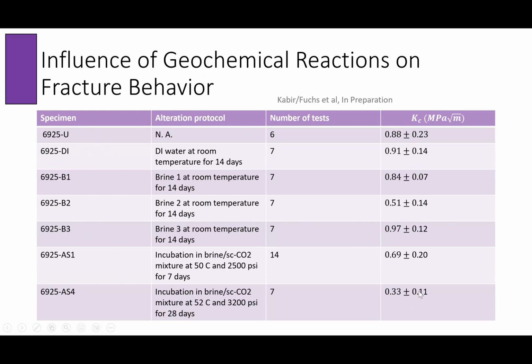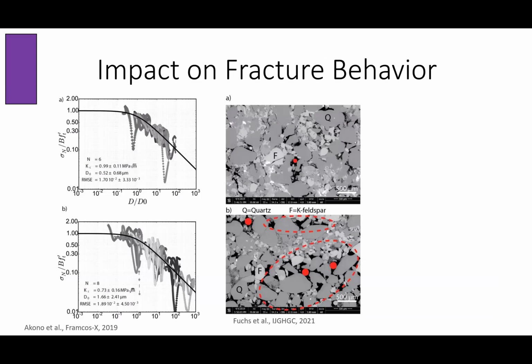But the highest decrease is when you have incubation in CO2 saturated brine at high temperature and high pressure for 4 weeks. So this first result is that when you have incubation under geologically relevant conditions, you have a decrease in the fracture toughness. And we even confirm it by taking into account the nonlinearity in the fracture behavior and using our energetic size effect law to analyze scratch tests conducted on both unaltered rock, but also rock that has been incubated in CO2 saturated brine. We still observe this decrease in the fracture toughness.